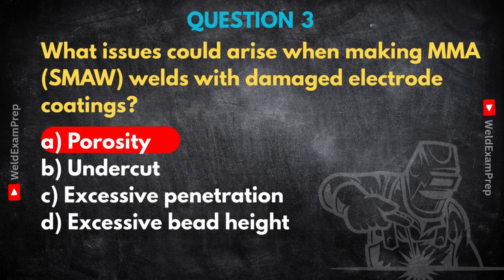Porosity. Why is that? Well, think about what the coating, the flux, actually does. It has several jobs, but a primary one is creating a shielding gas. This gas protects the molten weld pool from the surrounding air, specifically oxygen and nitrogen. Like a protective bubble. Exactly. Now, if that coating is damaged, chipped off, or cracked, it can't produce that consistent shield. Gaps appear in the protection. Oxygen and nitrogen from the atmosphere rush into the molten metal. And get trapped when it freezes?